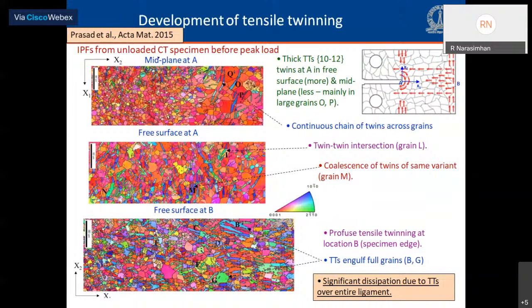The student who worked on it, Prasad, who is I think there in the audience, did a very thorough job, and he stitched together several optical metallographs and came up with this schematic on the right side, which depicts the twin development over the entire specimen, and it is ubiquitous, as you can see there. There's twinning all over the specimen, especially in the ligament at the far edge of the ligament at location B, near the notch tip at location A, above and below the notch tips.